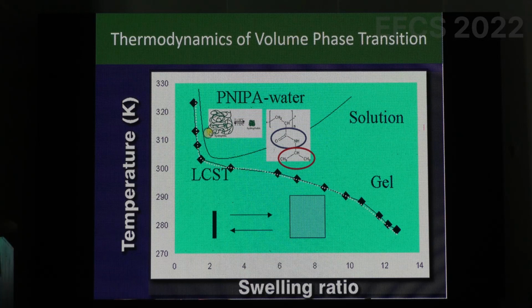Now, if you take this polymer and you cross-link it, and by cross-linking, it means that you stitch polymer chains together with small amounts of cross-links, then you get a gel. It doesn't dissolve, it just swells. So at low temperature, it would swell, and as you increase temperature, it collapses, right? And so this is how the gel would behave. And so this is what is called a swelling ratio of the gel.